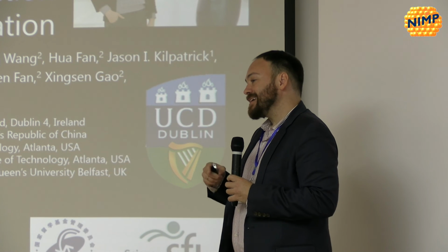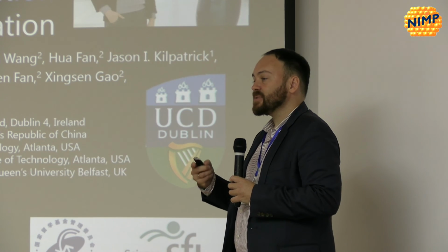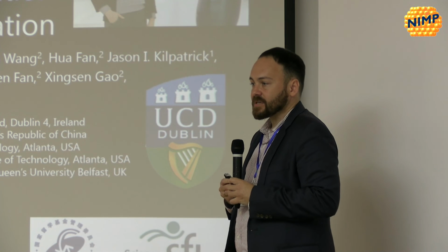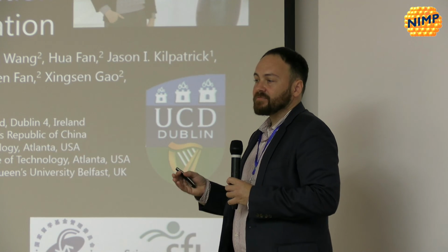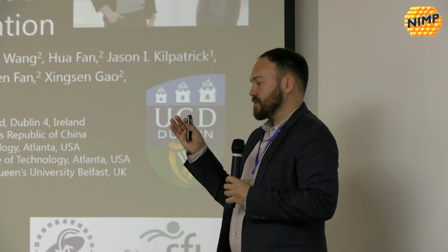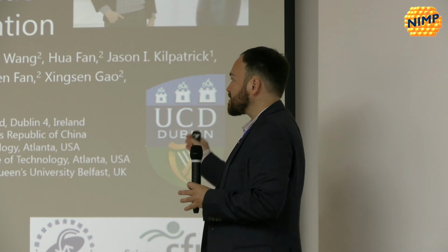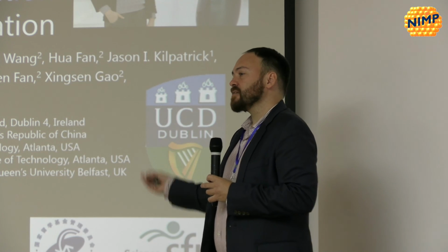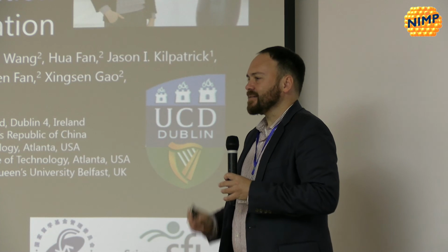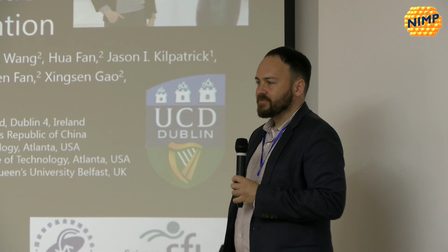The challenge would be if the tip geometry is changing over time, and it wasn't changing over time, or if the AFM has a closed loop scanner or not. I did find that if I would do a structure loaded with lithography, you draw the lines and that's where you want it to go. If I were to try to do another one on top of that old pattern, it didn't always line up, but that's more of an AFM issue.